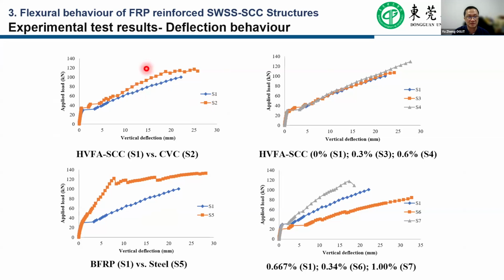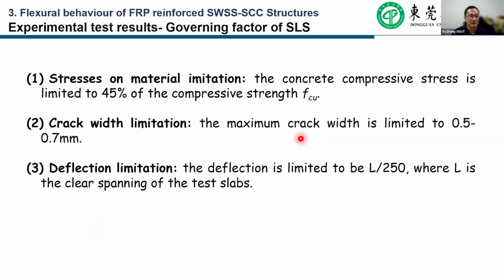For the deflection behavior, the influence factors can be expected, so they will not be discussed here. In this stage, we try to establish governing factors for the structure design for the service limit state. We established three factors. The first one is the stress limitation on the materials, including the concrete compressive strength. Furthermore, there is the crack width limitation, and the deflection limitation is limited to these values. And then the maximum crack width was limited to 0.5 to 0.7 millimeters.